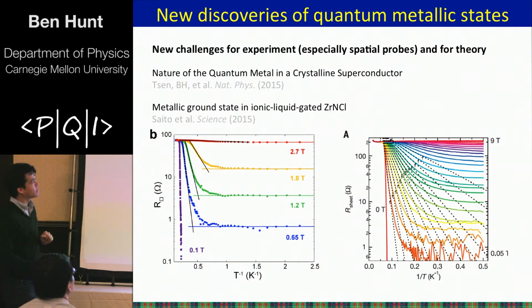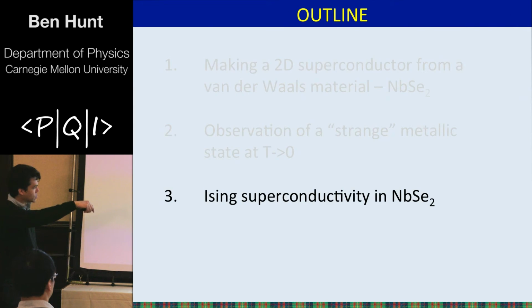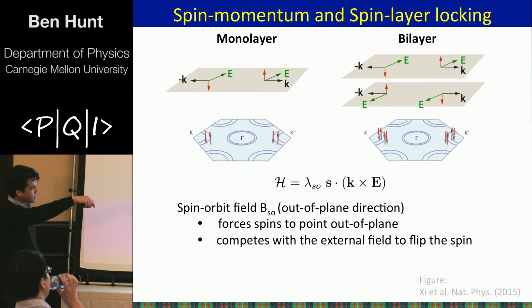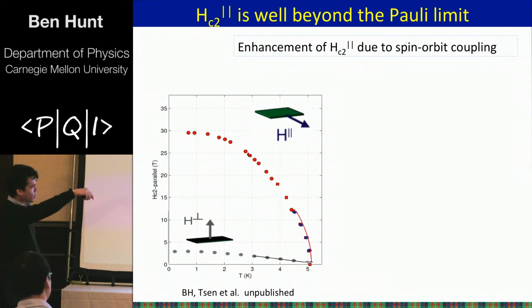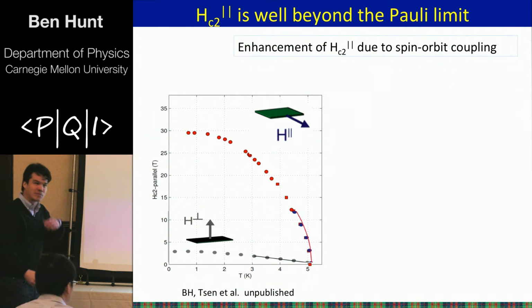I'm not going to have time to talk about this last topic, but I'll just summarize it in one slide. Whereas this quantum metal phase that we saw before is way down here, the normal phase, which we've quenched with a perpendicular magnetic field, is up here. If we apply an in-plane field, in stark contrast to what we see in a perpendicular field, in a parallel field the superconductivity survives up to 30 Tesla.